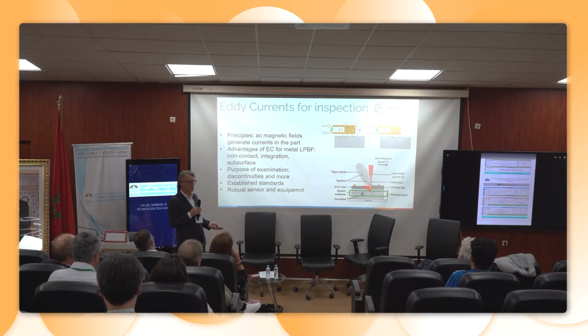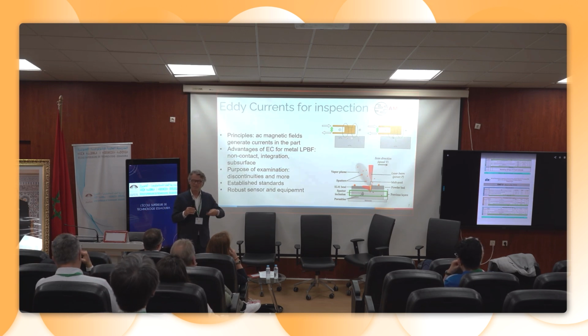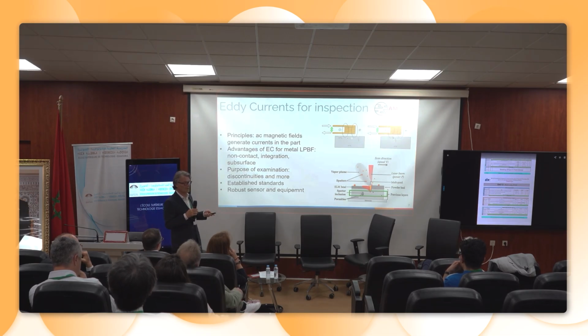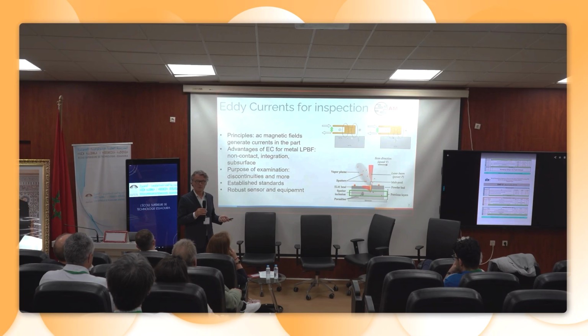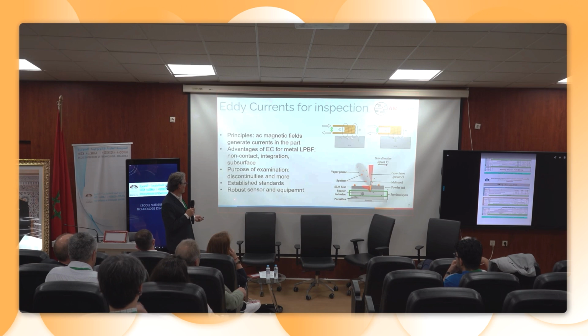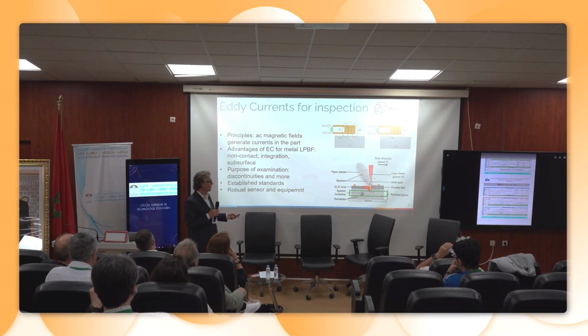One word about the NDT technique we are using. It's eddy current. Why? Because it's very robust. It provides surface information. And if you deposit your material layer by layer, actually you always have some surface that you can inspect. And at the end of the process, you may reconstruct your 3D model based on this non-destructive testing data. It works non-contact. It has a lot of standards. So in this project, we don't invent new standards. We use a rich corpus of standards in various industries. And it's robust equipment that can be integrated in what is called a hostile environment.